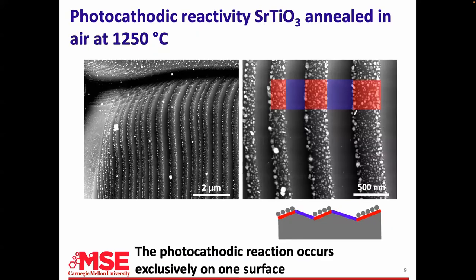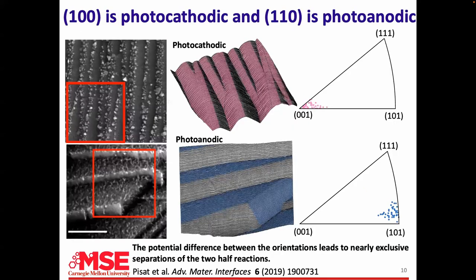With that, we can do experiments like this: a faceted surface after a silver reduction reaction. You can see the silver only clusters on one of the two types of facets — this is a photocathodic surface; the other does not like to reduce things. To summarize many experiments, the photocathodic surfaces are always the 100 orientation. You can also run oxidation reactions — the oxidation of manganese only collects on certain surfaces — and indexing those, the anodic surface is on 110. It's a really nice system.